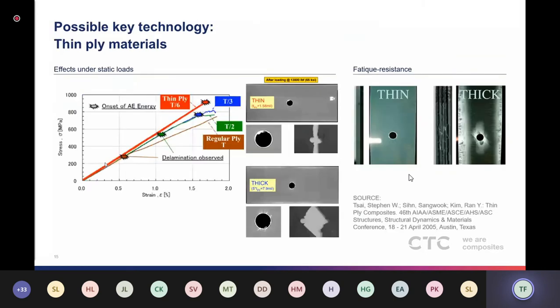One is the thin ply technology, which is indicated here and which I referenced earlier. thin ply technology basically uses one effect: if you load a regular ply, here indicated in brown, statically, then it fails at this point, but first delaminations and microcracks can be observed way before this. If you decrease the size here by half, here by 3, and here by 6, the area where microcracks occur moves much closer to the failure strain.